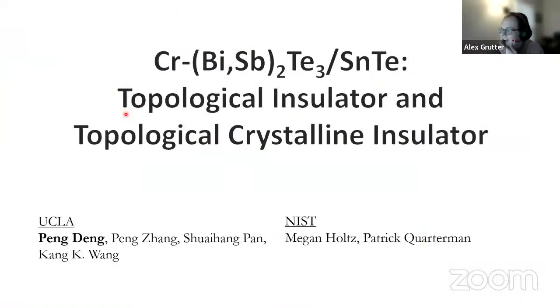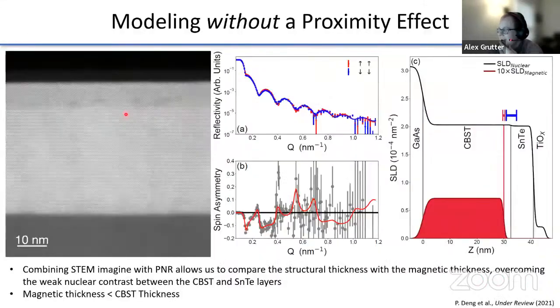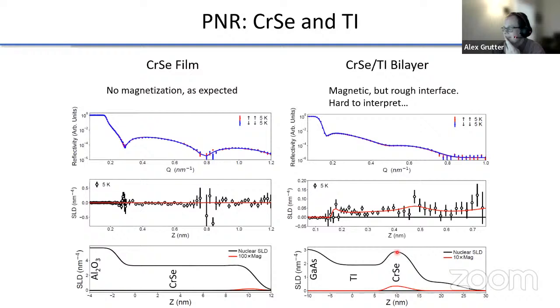And I gotta find this. Hang on, this is a pet issue of mine. Right. Okay, this right here. This does not look smooth, right? This looks like a real gradual slope. Over long ranges where you have these nanometer sized steps, it's not smooth. On a TEM level where you're probing local behavior, it's super sharp. And so you have to be so careful, right?